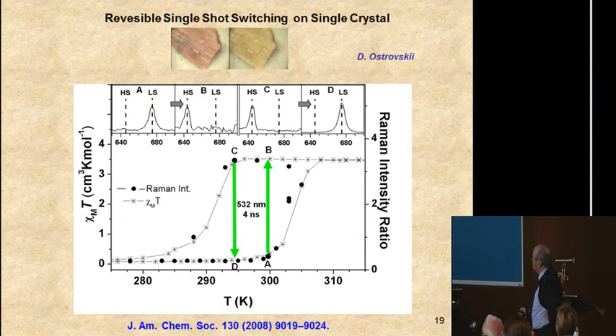If you send your pulse, you go from this point to this point. If you send your pulse at the point A here, you go from this spectrum to this one. You see, the low spin state disappears completely, and then you have the appearance of the high spin form. And what you can see is that the switching is complete. Here you are 100% low spin, and here you are 100% high spin. That means that you went from the point A to the point B, from low spin to the high spin, by sending only one pulse, one 4 nanosecond green pulse.